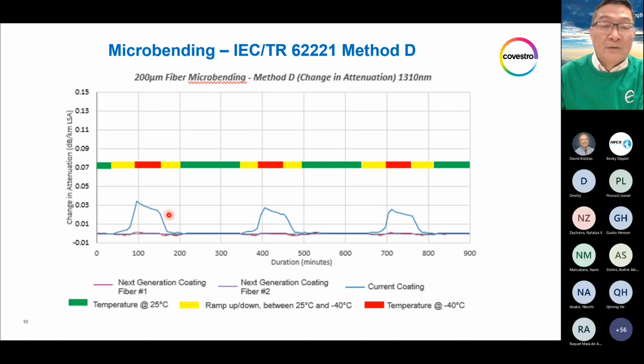So this is one cycle, right? One cycle. Then the cycle starts again and again. In this case, the cycle was repeated 3 times, and the actual attenuation was measured by an OTDR machine. What is shown here is not the absolute value of attenuation. Actually, it is the change in attenuation. It measures the changes in attenuation starting from the beginning of the cycle. So through the complete cycle, what is shown here is the maximum change in the whole process.